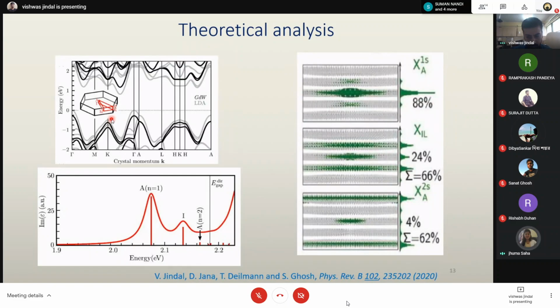Can I comment something? Yeah. So I think what Vishwas is trying to say is this is not the band gap, we say it as optical band gap. So how can you probe this material with optics? With light you cannot do an absorption or any measurement from gamma to K point, right? The K of light is very small, so you virtually do a vertical transition on the K axis. So with light, you can probe only at a fixed K from one band to another.